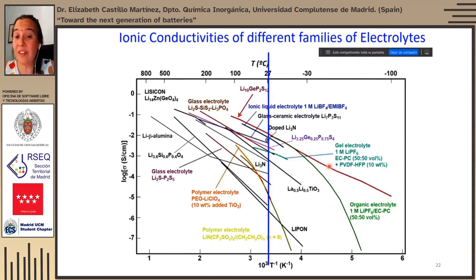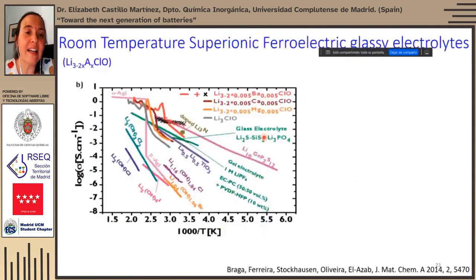And actually, some of the sulfides have been proposed to have similar conductivities as well. However, what is more striking, and this is quite recent, is that there are some lithium-rich or sodium-rich glass electrolytes, which are derived from the antiperovskite structure, that show conductivities very comparable to those of the liquid electrolyte, and even higher than that of the sulfide.